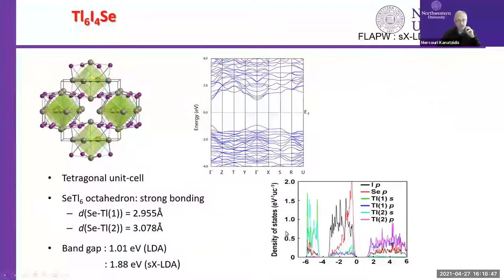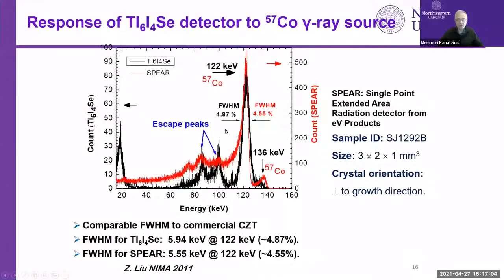It's a tetragonal structure. Here's the electronic structure. It is a semiconductor. This is the valence band, this is the conduction band, and this is the direct band gap. And so it looks good. It has low enough effective masses. So we spent some time on this, and almost 10 years ago, we observed this spectrum, which is exactly what we're looking for. We're looking for the material to be able to resolve the energy of gamma rays, such as a cobalt 57 radioactive source, and to give us the spectrum of the gamma rays from cobalt.